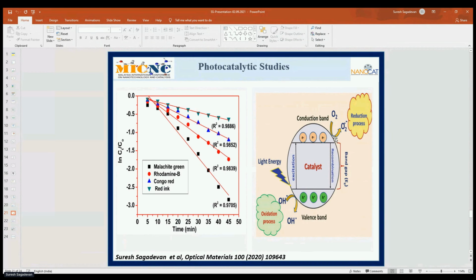oxygen species to form superoxide radicals, which are also responsible for the degradation reaction of adsorbed dyes like malachite green, rhodamine B, Congo red, and red ink solutions. So the photocatalytic reaction by this composite occurs through the well-known mechanism of visible light driven electron excitation from the valence band to the conduction band, and by production of reactive intermediate free radical species, where all this happens sequentially to degrade these four dyes: malachite green, rhodamine B, Congo red, and red ink.